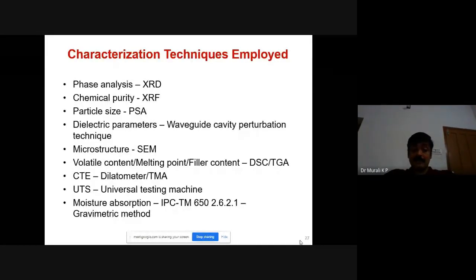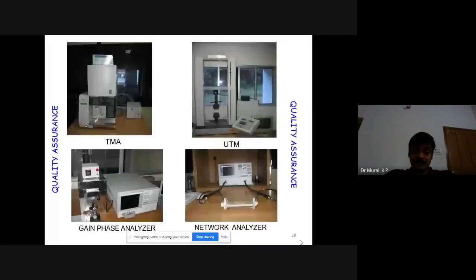Then CTE using the dilatometer or TMA, and UTS. Universal testing machine can be used for ultimate tensile strength, moisture absorption using the gravimetric method. There is an IPC TM method. So most of them you must be familiar with.